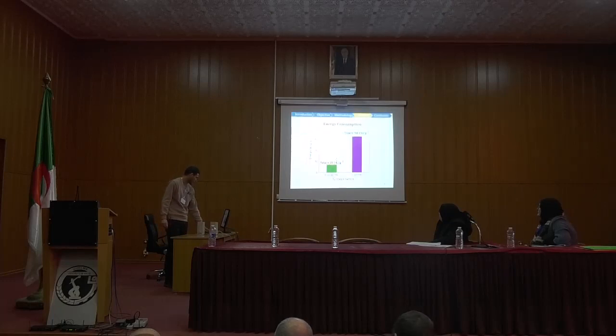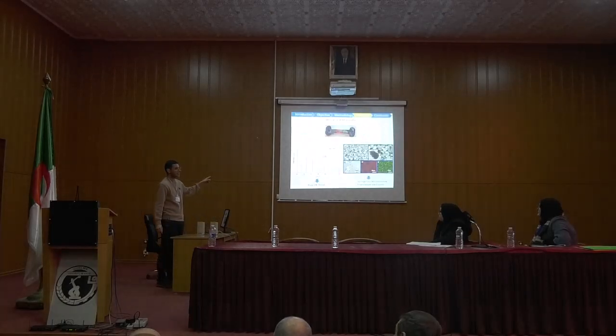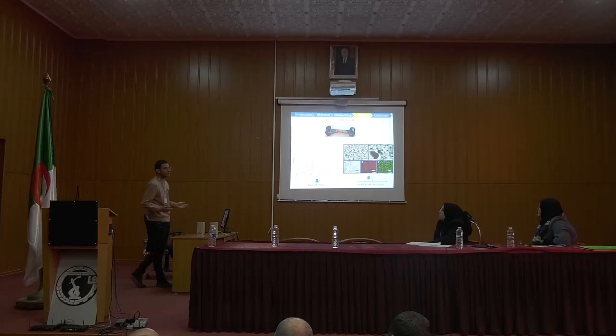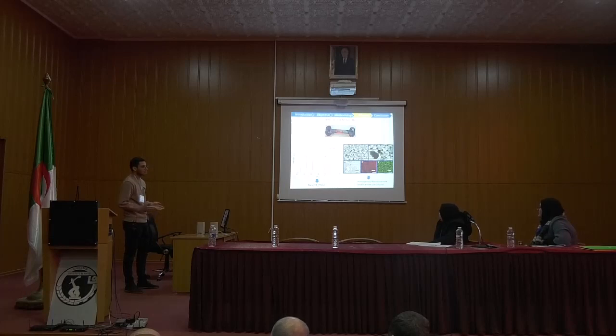Well, I show here that I have pure zirconium diboride. So we cannot say that there is a difference between the commercial one and the synthesized one. Also, the commercial producers use a synthesis method to produce it, so I think it's the same. And also, I show in the X-ray that I have a pure phase zirconium diboride, so I don't have impurities here. So it seems like phase pure. Thank you.